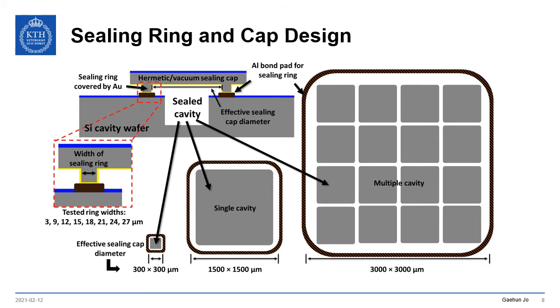Different sealing ring widths from 3 to 27 micrometers were investigated. At the same time, 3 different dimensions of cavities were investigated to verify our packaging method. The caps with dimensions of 300 by 300 micrometers and 1500 by 1500 micrometers are designed to test a single cavity. And the caps with the dimension of 3000 by 3000 micrometers are designed to test multiple cavities. Encapsulating multiple devices by a single sealing cap can give the benefit of reducing sealing footprint.